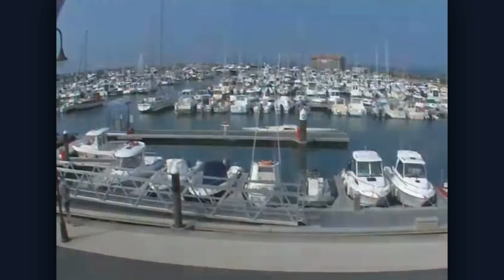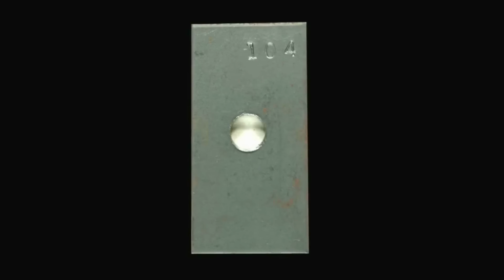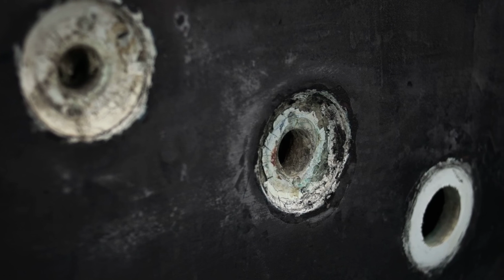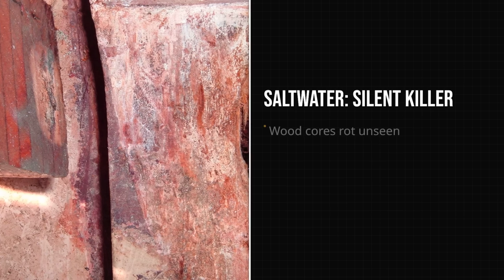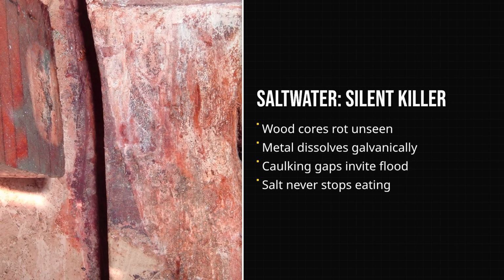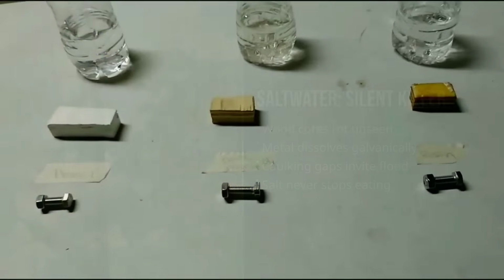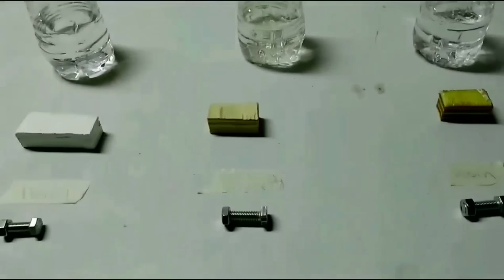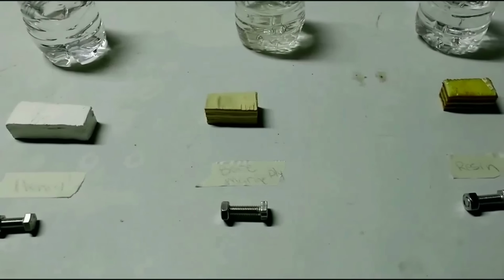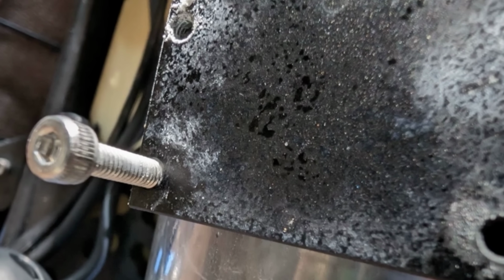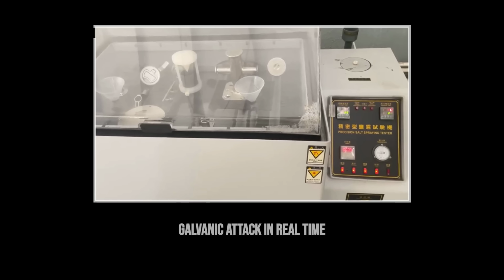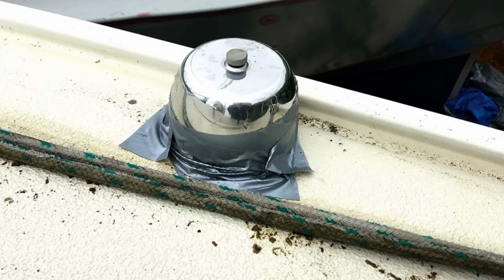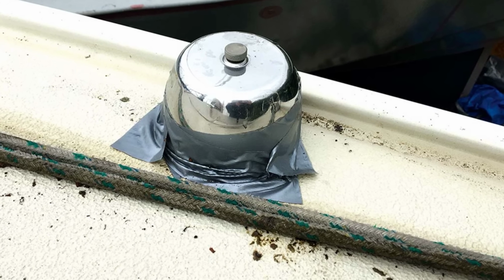Here is the reality of the saltwater environment. It is one of the most corrosive conditions any engineered structure can face. It finds every path water is allowed to travel, and it destroys every material that was not specifically designed to resist it. Organic core materials absorb moisture, swell, and rot. Dissimilar metals in contact corrode electrochemically in the presence of salt brine. Poorly executed joints and penetrations become water entry points that work silently for years before you ever feel the consequences.